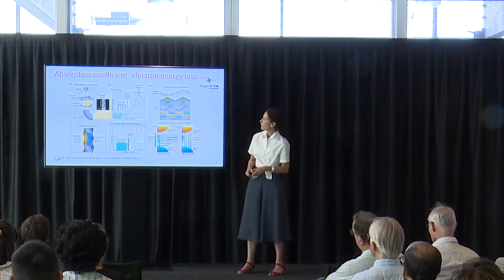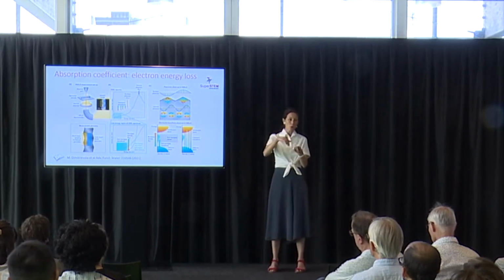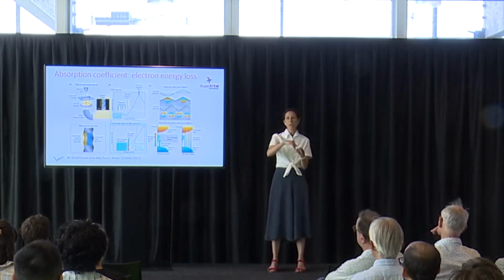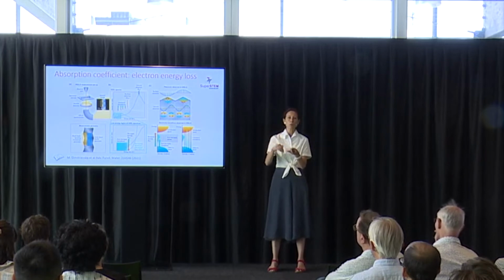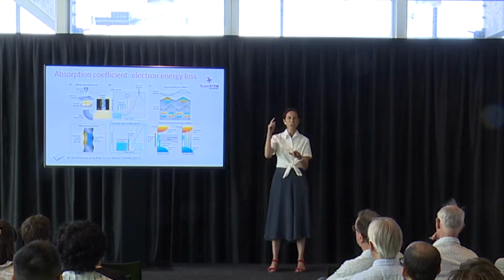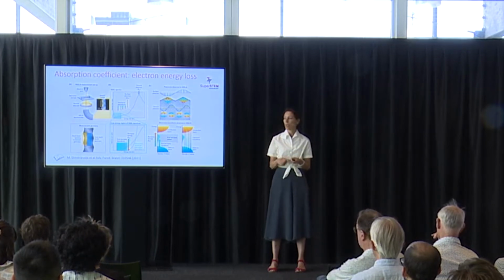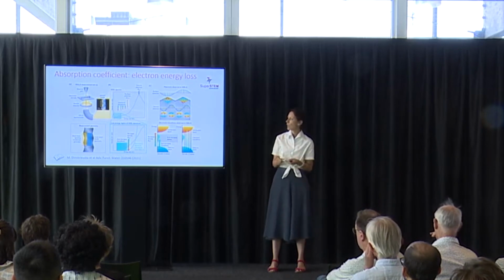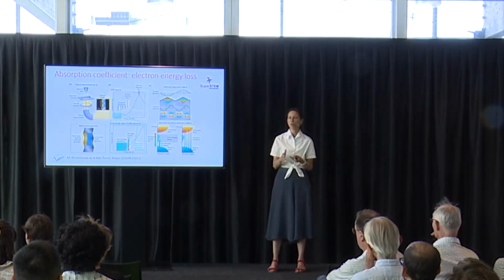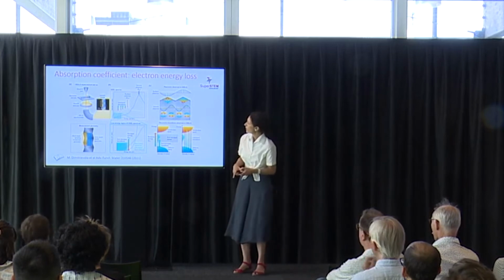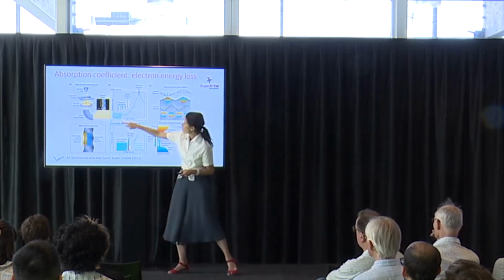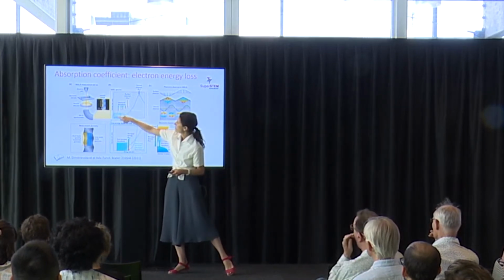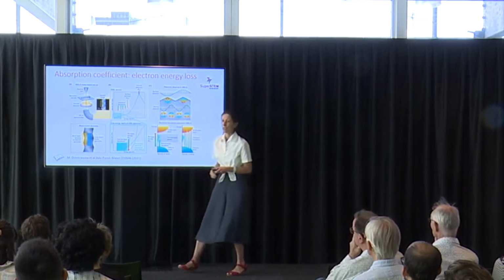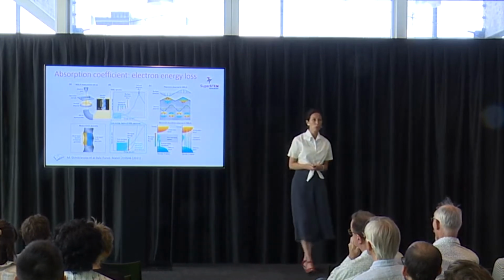You can do it by illuminating the center of the wire or in a grazing zone. In the center of the nanowire, you will mostly have absorption through the bulk plasmons, what they call bulk plasmon, which is transitions at the more core levels of the elements. While if you go into the grazing zone, then you will have more the transitions that are close to the band gap. And this is what you see here. The measurements show a very high absorption in the grazing zone, and you have many transitions here that contribute to absorption. I will explain later on what these are.